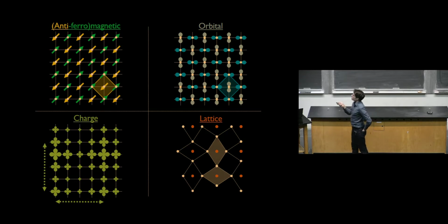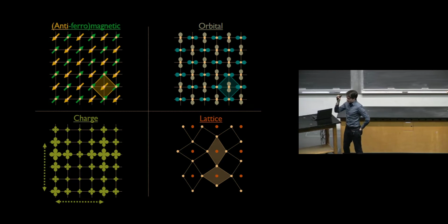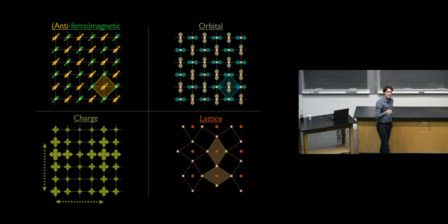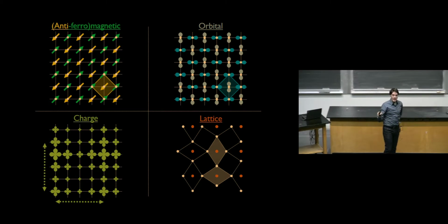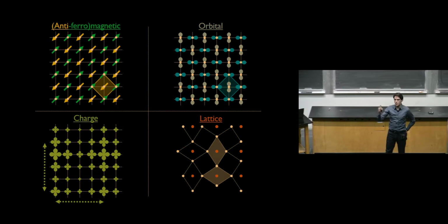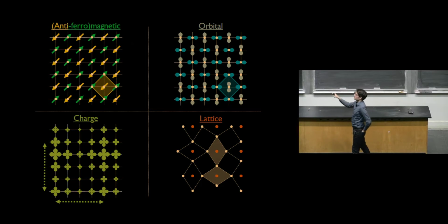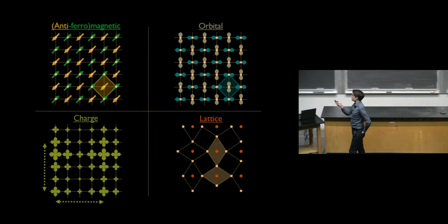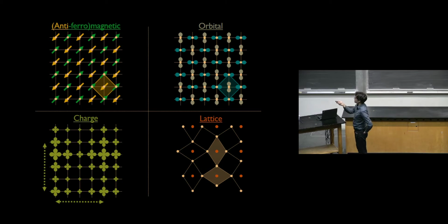You can have a charge order state where now the amount of electrons that you have at each lattice site changes as a function of the lattice, again, in a periodic way. So you have these kinds of modulations of the charge, which has a given period. In this case, it has a period of 4 unit cells. Okay, so this grid is the original lattice, and the period of this modulation is 4 unit cells in this direction and in this direction.